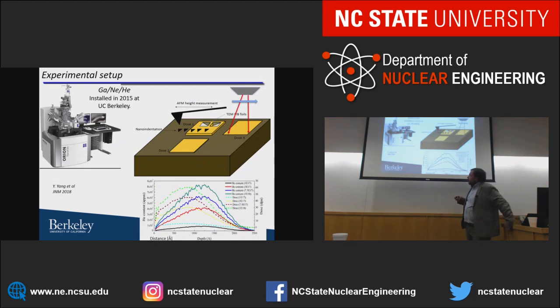A few years ago, we won an NSF MRI where we purchased a gallium, neon, and helium multi-ion beam microscope. It's really meant for imaging, using helium and neon ions for imaging, not necessarily for anything else. It's a bio thing. At the time, I was very interested in bio. Anyway, we actually kind of misuse it and use it as a nano accelerator. We have a 0.6 nanometer beam of helium ions we can raster across surfaces. And so we implant 5 by 5 or 10 by 10 micron fields in our material and get some dose in there, and then do nanoindentation, atomic force microscopy, TEM lift-outs, everything you want to know about helium implantations.